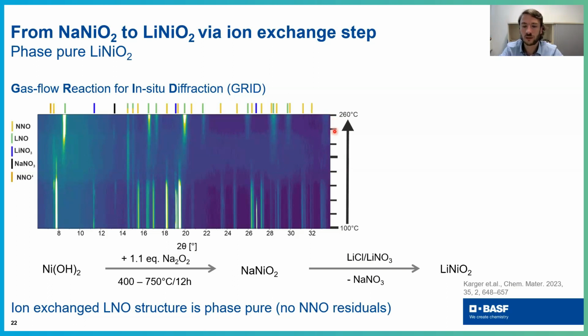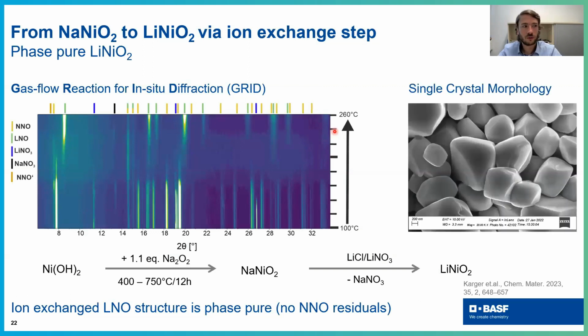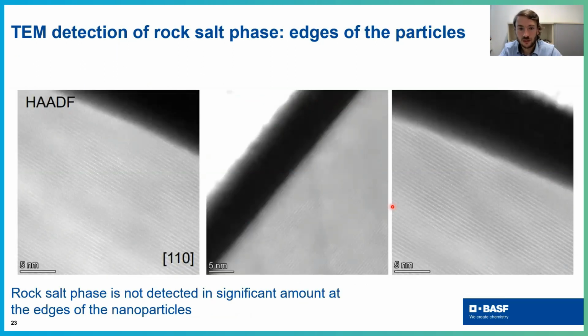If you then take out the sample and wash it, you will see your single crystals, which are now lithium nickel oxide crystals, which have the same size and essentially the same shape as you had before for sodium nickel oxide. Surprisingly, the surface looks quite clean. Although we have to wash the material, we have a layered structure at our LNO surface.